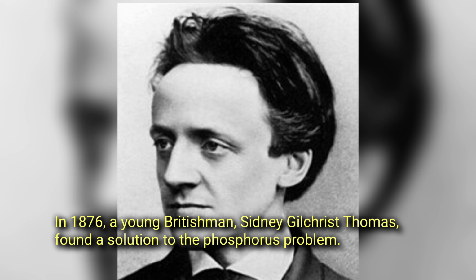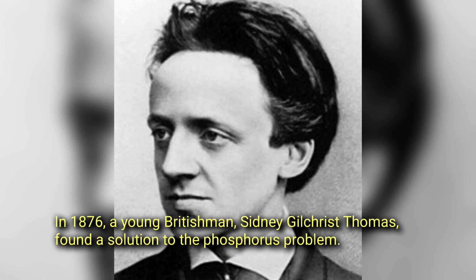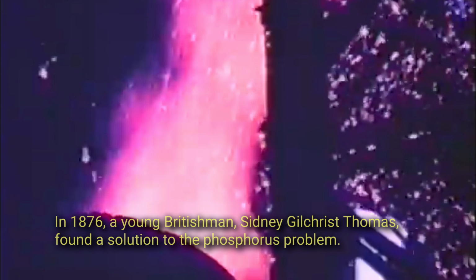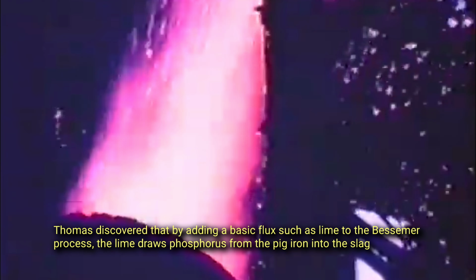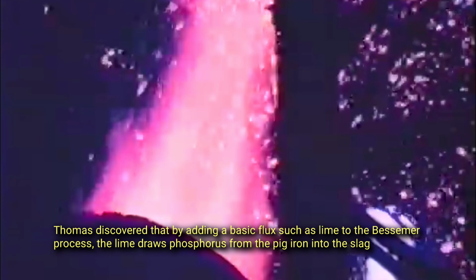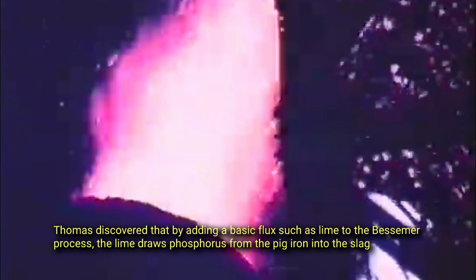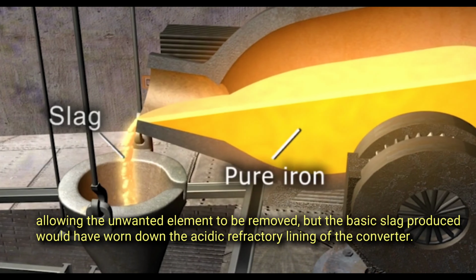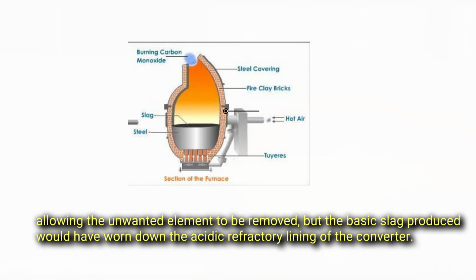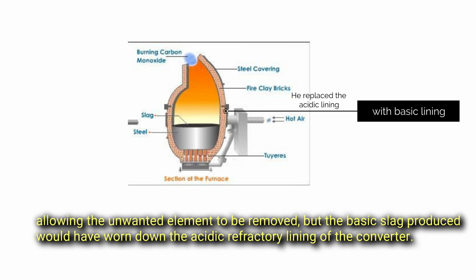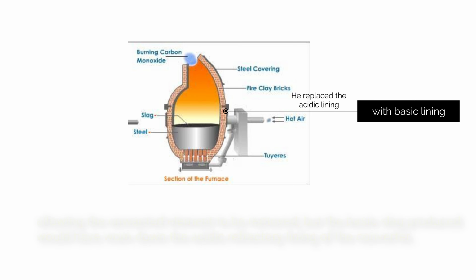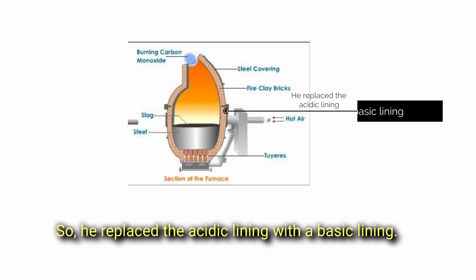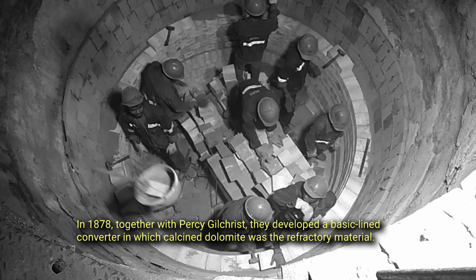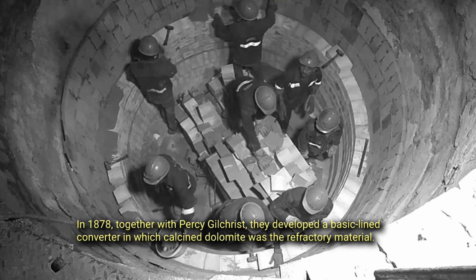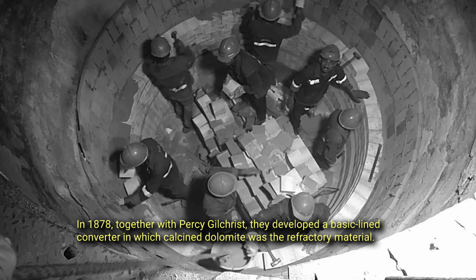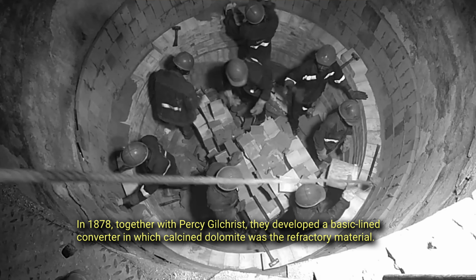In 1876, a young Britishman, Sidney Gilchrist Thomas, found a solution to the phosphorus problem. Thomas discovered that by adding a basic flux such as lime to the Bessemer process, the lime draws phosphorus from the pig iron into the slag, allowing the unwanted element to be removed. But the basic slag produced would have worn down the acidic refractory lining of the converter. So he replaced the acidic lining with a basic lining. In 1878, together with Percy Gilchrist, they developed a basic-lined converter in which calcined dolomite was the refractory material.